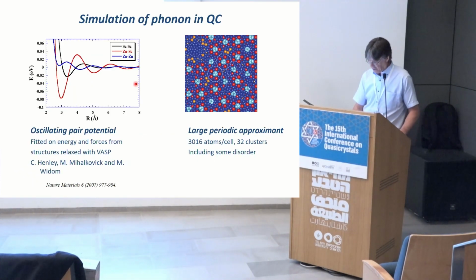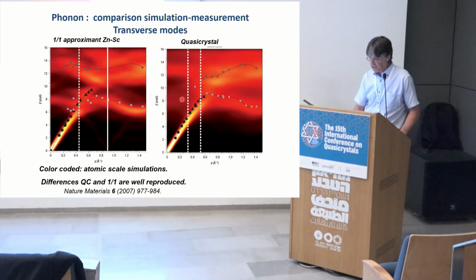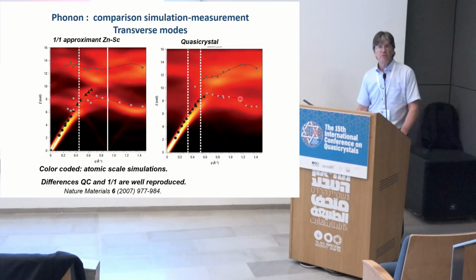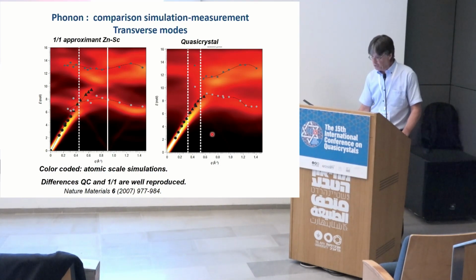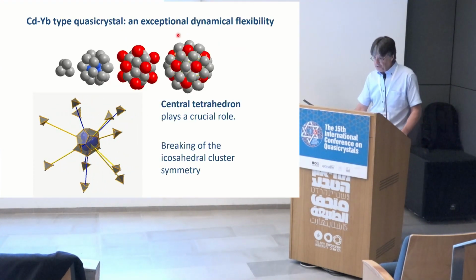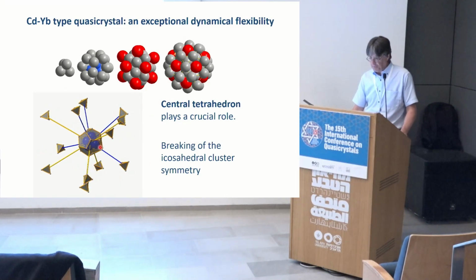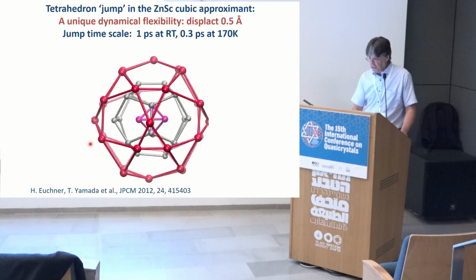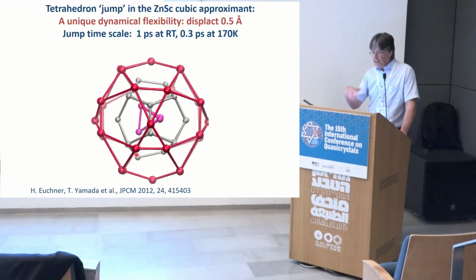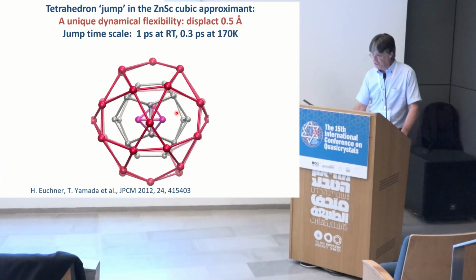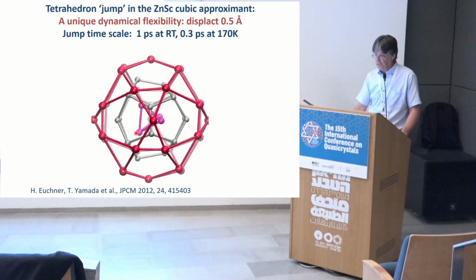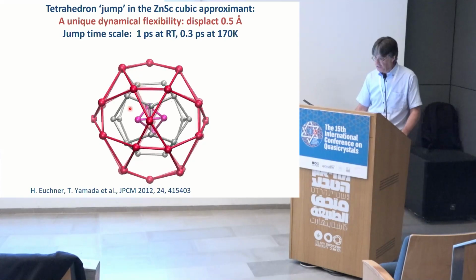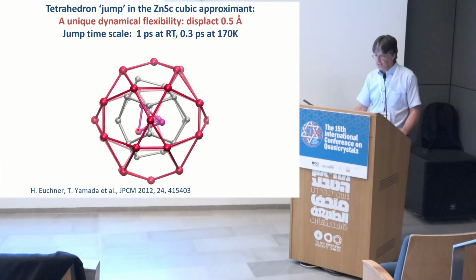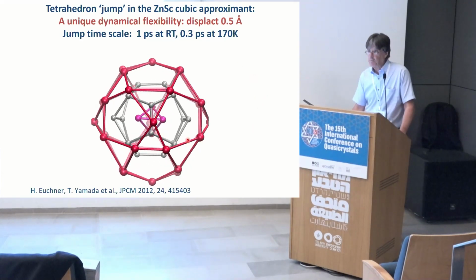Nevertheless, with the help of Marek Mihalkovic, we had a lot of simulations done, which do reproduce pretty well what is observed experimentally, which just demonstrates that we can, using large periodic approximants, reproduce a quasicrystal. And we also could show that the central tetrahedron, which is playing a quite important role, is actually moving constantly, even at relatively low temperature. It's 170K. So you see the central tetrahedron is constantly reorienting, and when it's reorienting, it is distorting the neighboring shells. So that's what is going on in the 1-1 cubic approximant.